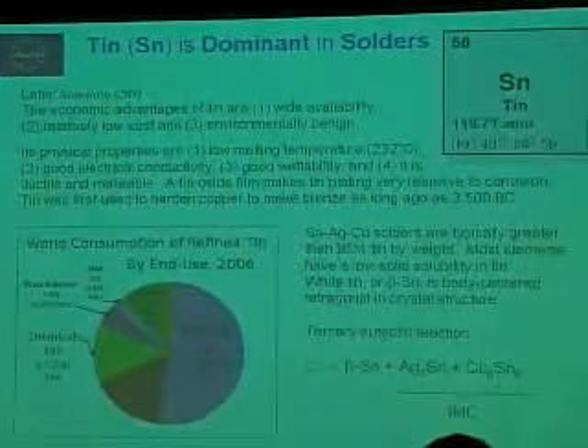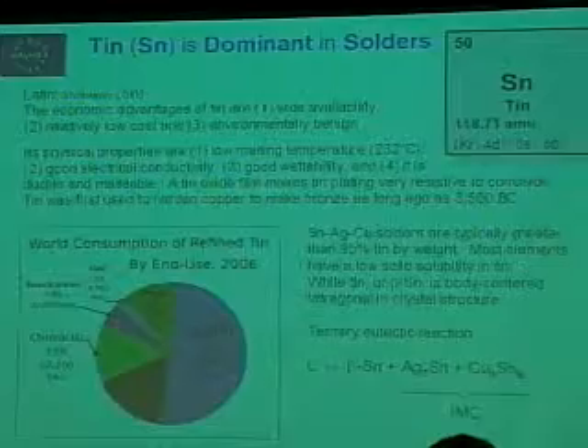Okay, I did want to say a little bit about tin, because you'll note in the SAC solders, tin is dominant. It's 95, 96, toward 97% tin. So we really have a tin-rich material. Tin plays a big role in the intermetallic formation and the behavior of this material. So tin is obviously a nice choice because it has a low melting temperature. Tin itself melts at 232. It's widely available, low cost, environmentally benign. That's really the main thing here. It actually is a pretty good electrical conductor. It has good wettability. One of the things I thought was interesting is tin was actually first used to harden copper to make bronze 3500 BC. That's a long time ago. This is not a new material. Copper isn't a new material either.